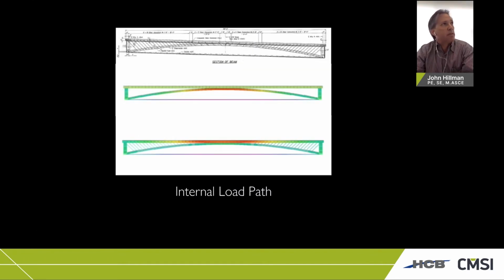And the simplest embodiment, this is about a 18-meter beam we did on a project up in Maine back in 2009. And so what you see is when you put the shell in place, it's self-supporting on its own. Then we fill the concrete in the rib to get the compression arch. The deck is placed after that, and ironically what happens is when you place the deck, you actually pre-compress the concrete, which is to your benefit because concrete doesn't fail in compression. Concrete fails usually in shear or tension. So by pre-compressing the concrete, we actually maintain the capacity of the concrete at a higher level as we get to the ultimate limit state. I'll show you that later.